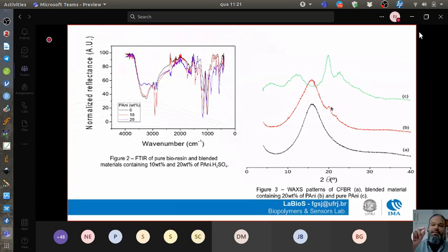Okay, so we can imagine that this dispersed PANI crystalline phase will be useful to the percolation under pressure. And these sensors, in this case where we are talking about pressure sensors using conducting blends, they work following this kind of percolation. So when you press this kind of material, you are putting all these small conducting crystals closer, which increases the electrical conductivity.